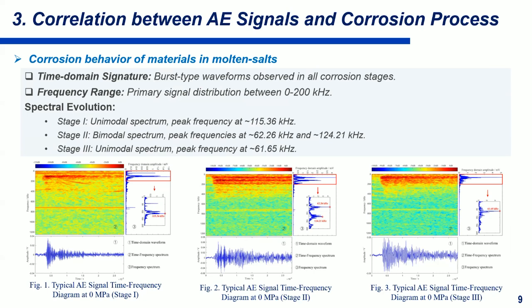In these results, in stage 1, the spectrum is unimodal. The peak frequency is about 115 kilohertz. But in stage 2, the spectrum is bimodal, and there are two peaks. There is another new mechanism in this stage. And in stage 3, the spectrum turns to unimodal again, and the peak frequency is about 61 kilohertz. So the mechanism of the corrosion is different.